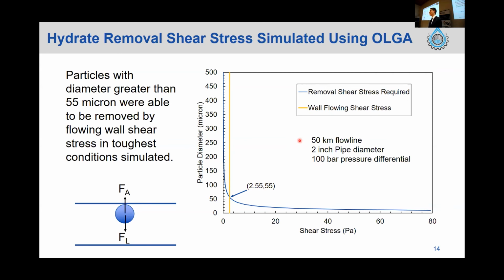And so what was taken from Olga was the wall flowing shear stresses. And then basically that was used to calculate the lift force that might be experienced by a hydrate particle that adhered to the wall. And that was basically balanced against the adhesion force that was measured, and it was used as the 8 millinewton per meter value to be conservative, the highest value recorded. So this basically shows that the shear stress required is dependent on that hydrate particle diameter.